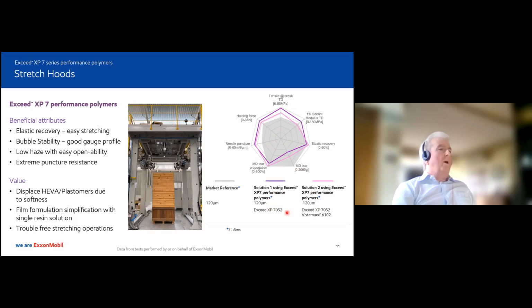The feedback that we've generally had from the marketplace has been pretty positive when it comes to the complement of properties. And one of the things that we do get fed back is that they find generally that the stretching operation on the stretch hood machine tends to run pretty much trouble-free. And what that really means is that if you're going to encounter really bad tearing and stuff, you'll hear about it then. But generally, it works very well. So there's a nice simplified solution exploiting, again, the melt strength and the toughness of the resin, and the lower density, providing some more elastic recovery, which can be improved upon, as I said, with a blend partner.